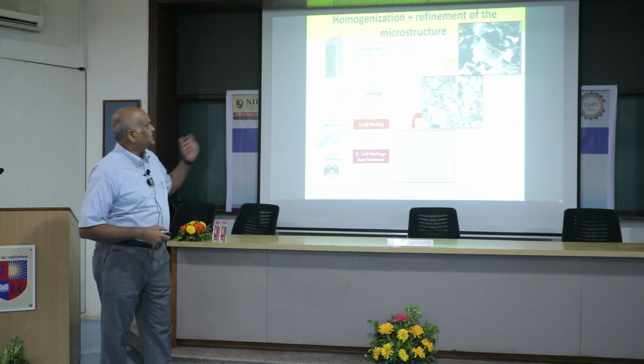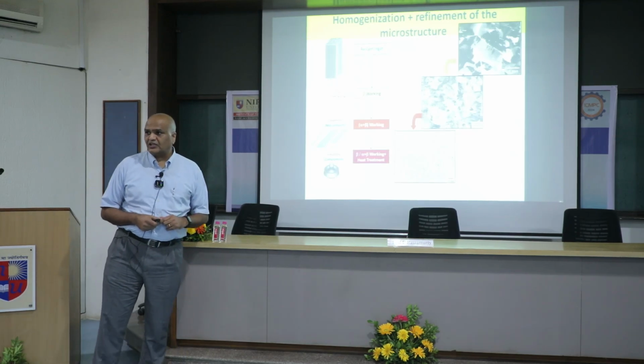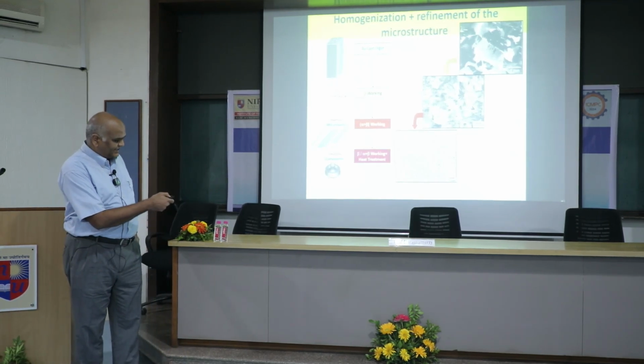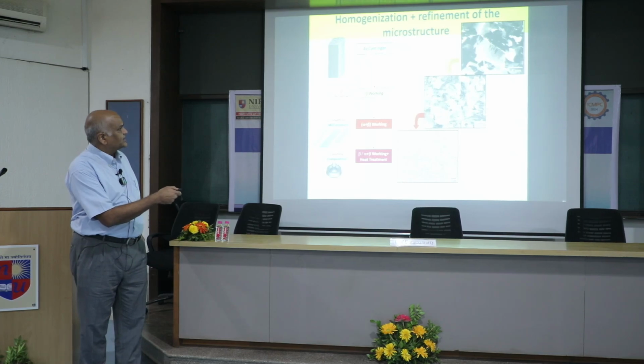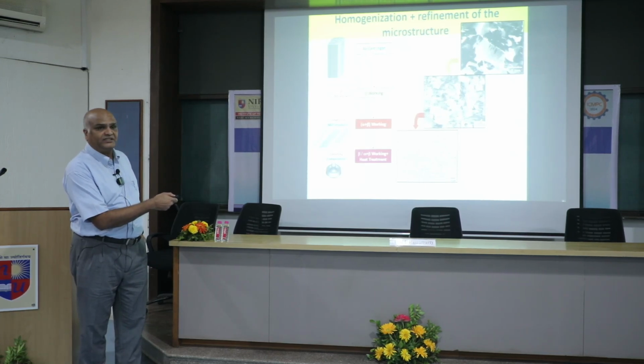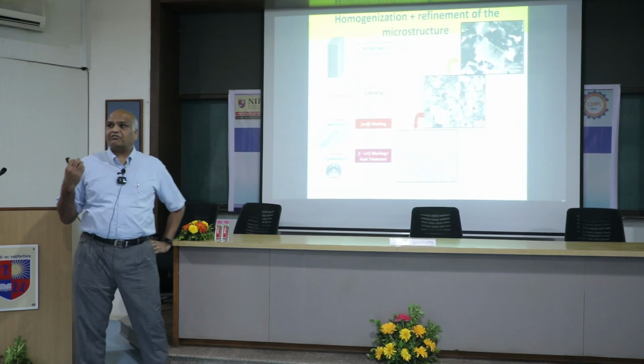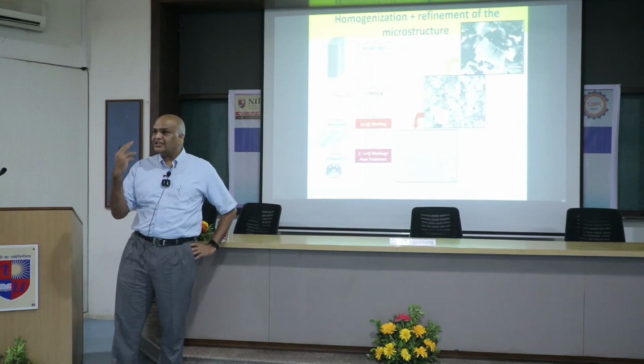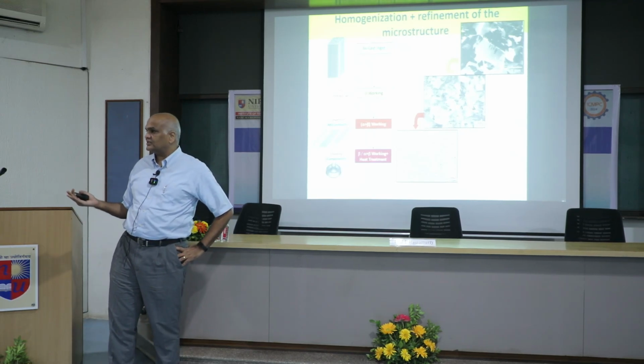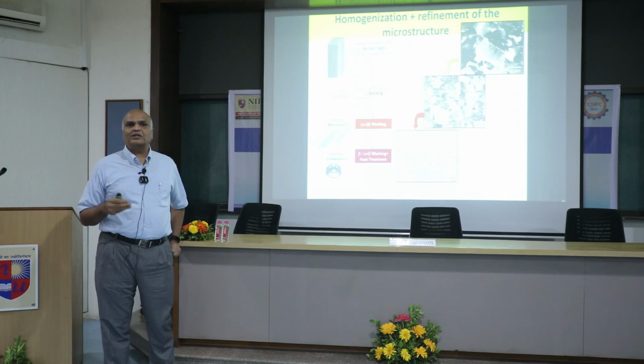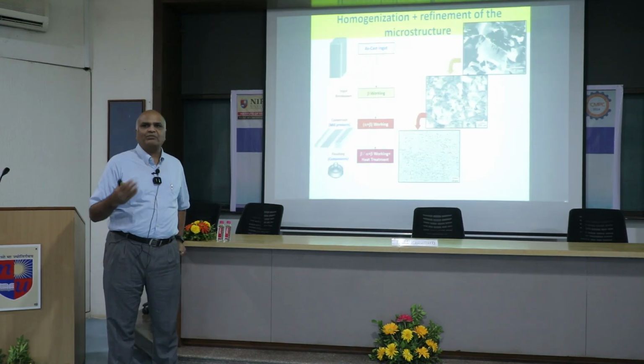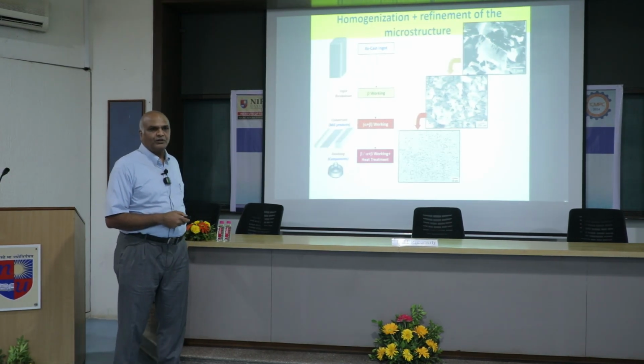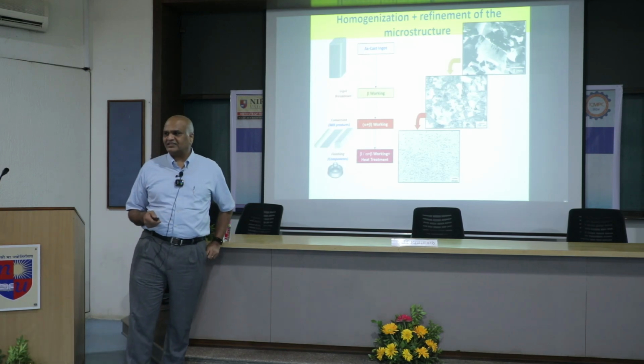For example, this is a Ti64 alloy, a titanium alloy. In the as-cast structure, you see the microstructure is very coarse. This is a 5 millimeter bar. You can have grain sizes that are 2 millimeters, very large. Typically in most steels or alloys, you will have grain sizes on the micron length scale, 10 microns, 20 microns. 1000 microns is a millimeter.